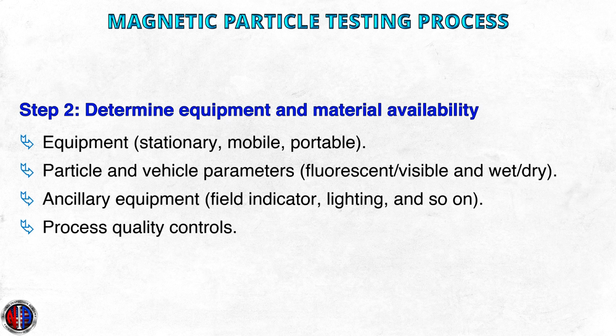Stationary benches are generally considered more efficient in terms of production rate and more versatile in terms of magnetizing current options. Wet suspension or dry particles. In general, wet suspension particles are used with stationary equipment such as wet horizontal units and are preferred for smoother surfaces. These particles are also available in pressurized cans for use with portable equipment. However, the dry particles are most commonly used with AC yokes, DC prods, and permanent magnets. Visible versus fluorescent particles. The most visually sensitive particles are fluorescent. It is always advisable to use dry particles with colors that contrast best with the test surface, but with fluorescent particles, the background is generally black or very dark purple when observing the test under UVA light.